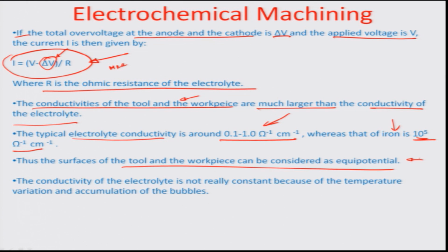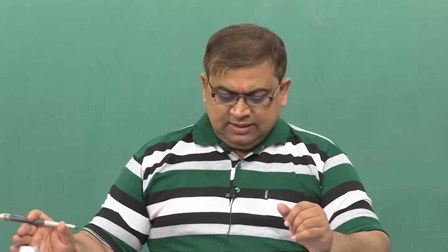We are not really concerned with the potential effects that would happen because of disparities on the surface in terms of roughness, asperities or valleys, and so as far as our potential calculations at a macro level go, we consider it to be atomically flat. But that is actually an assumption, because in reality when we talk about micromachining processes, and this goes to the lower scale, we have to consider even those asperities and the potential concentration effect that they would assume on the surface, which will result in a lot of differences in terms of the machining that is going to take place.